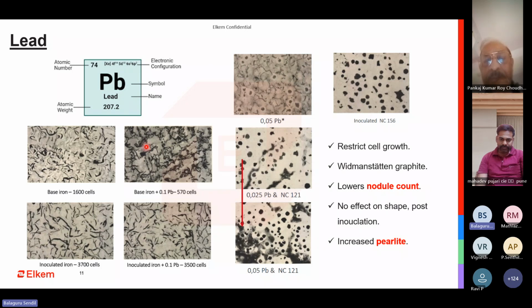In terms of gray iron, if your lead is high, it is going to kill your number of eutectic cells, which again translates to a not so uniform type A microstructure. And in ductile iron, in an uninoculated condition, it is dangerous. When you are inoculating, up to some extent it is manageable. More than that, it cannot be managed, and it only reduces your nodule count. It doesn't affect the shape of a nodule.